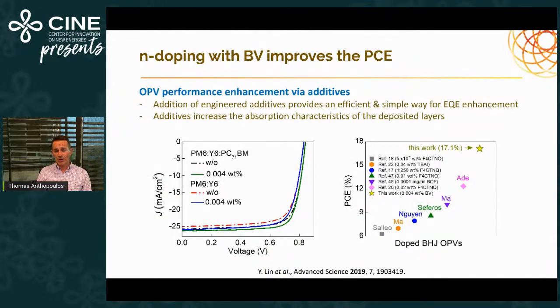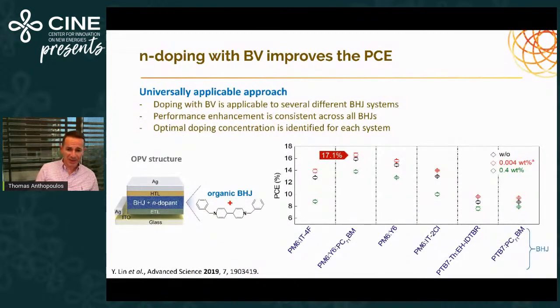So essentially, what we've been able to show with this BV N-type doping device, we show essentially OPVs with an efficiency of 17.1%. Since then, we've been, of course, expanding this work, and we extended to a number of bulk heterojunctions, and we show that essentially BV is a generic, it's a universal dopant, and appears to have a positive effect for a lot of relevant bulk heterojunction systems.